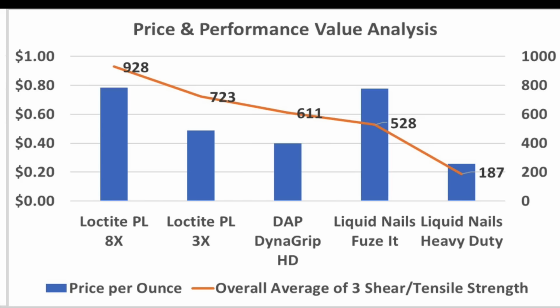In the tensile strength test, both PL8X and 3X were so strong that the wood failed before the adhesive. In the wood tensile strength test, PL8X experienced 2 wood failures. So both of these products are stronger than the other brands by a larger margin than what's reflected on the chart. From a value perspective, PL8X is the most expensive and strongest.